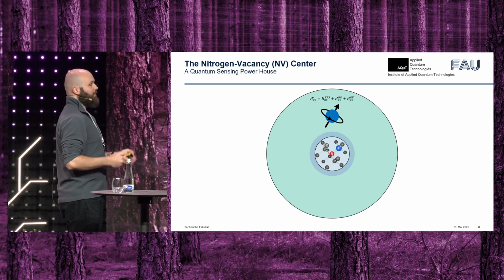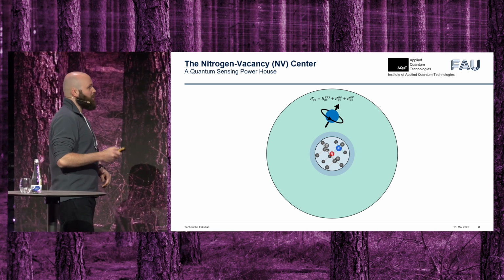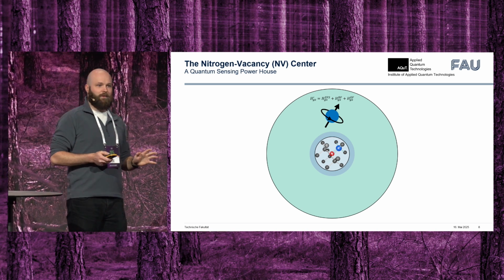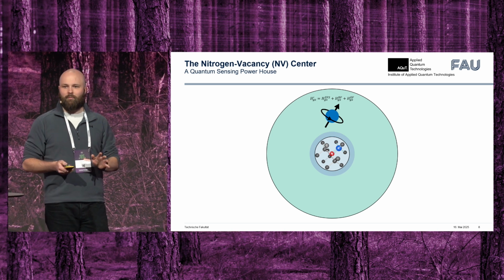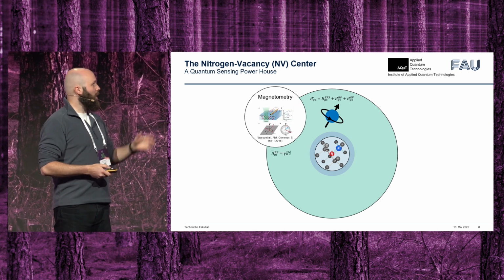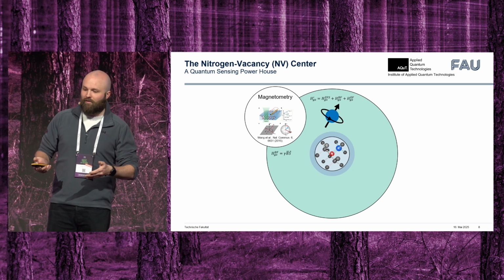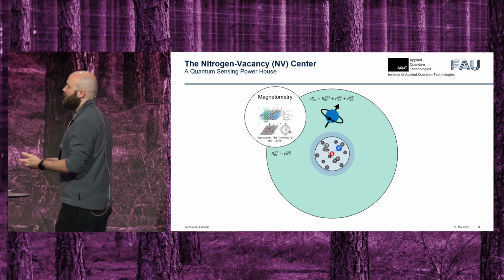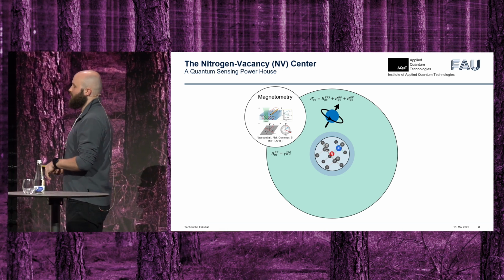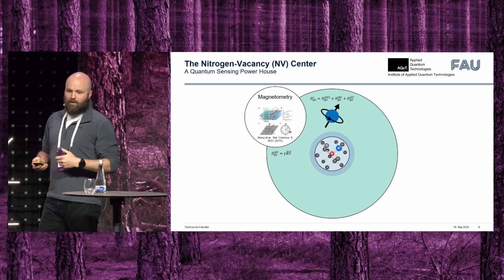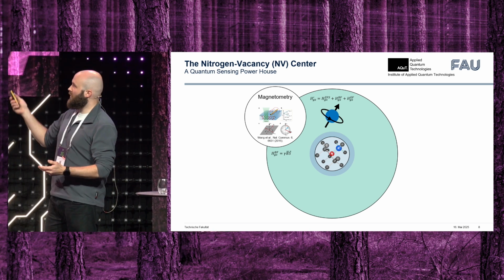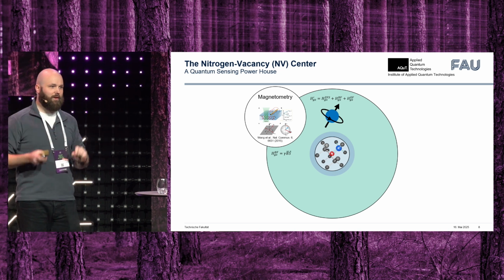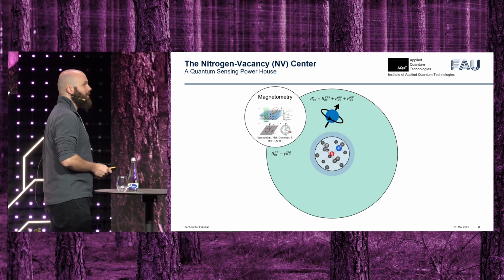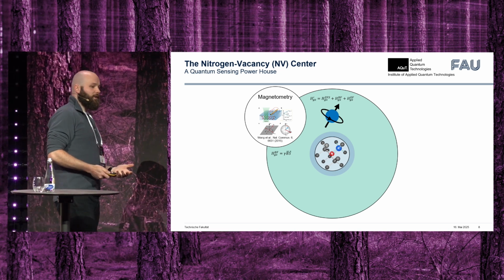But as I mentioned, it's good because we know all the interactions that the NV center's spin system has with the environment. We know how it interacts with magnetic fields, and this lets us use this high susceptibility to its environment to our advantage. And we can detect magnetic fields using the NV center, so basically this missing carbon atom in the carbon lattice, and we can probe magnetic fields.